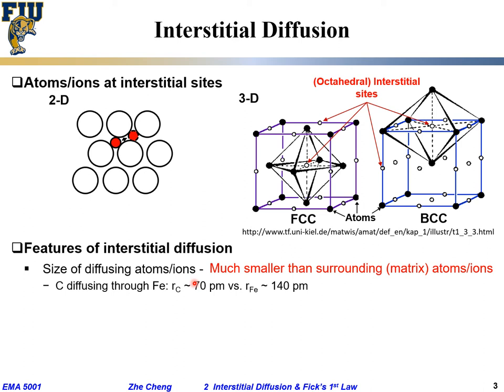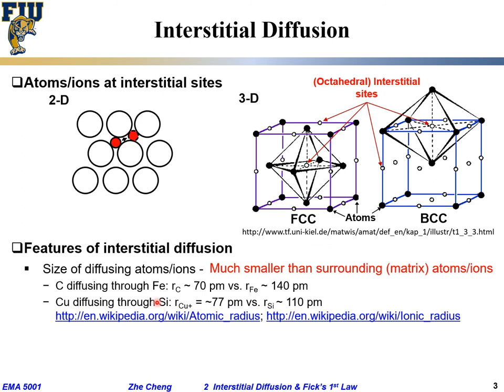Similarly, copper diffusion in silicon. The carbon diffusion in iron is important for any steel production, any tool. This guy, copper diffusion in silicon, is critical in semiconductor. People know copper is a notorious poison for any silicon-based semiconductor device, because copper's element size is much smaller than silicon size. And as you can imagine, if there's a little bit of copper contamination in the device, the copper will quickly go through the silicon and make your semiconductor device lossy or completely bad. Lossy means it consumes more energy than it should. It gives more heat. And completely bad means your p-n junction got shunted, got shorted.